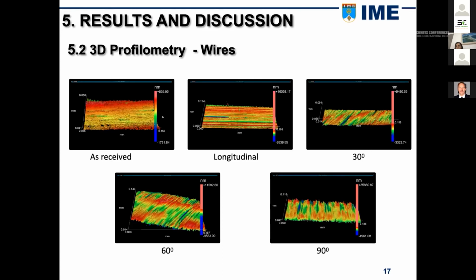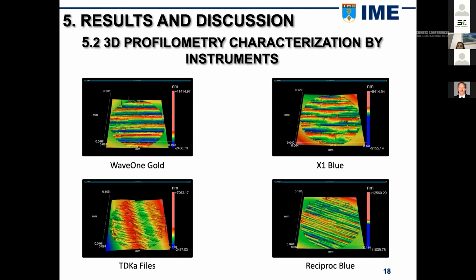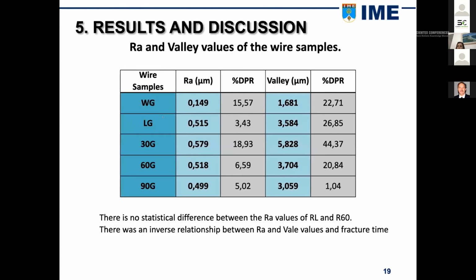Both the roughness parameters, RA and valley depth, of the wires and the files were quantified using a profilometer. In the table, it's possible to observe the difference in RA and valley depth values in samples without grooves. There is no statistical difference between the RA values of the samples with longitudinal grooves and the samples with 60-degree grooves. There was an inverse relationship between the values of RA and the fracture time, as can be seen in the table with the values of time until fracture in the rotating bending test.